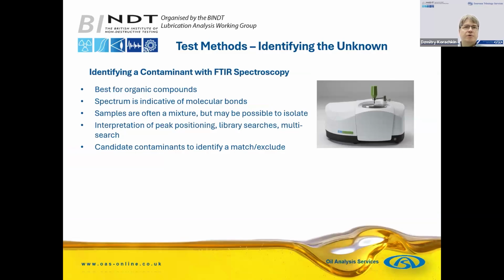Another useful method is infrared spectroscopy. This works best for organic compounds. The spectrum that's produced is indicative of molecular bonds present in the sample. When samples are a mixture, it may be possible to isolate the samples and test each component individually. But we also have access to previously tested samples and library spectra, and can not only identify a contaminant, but we may be able to exclude certain contaminants.